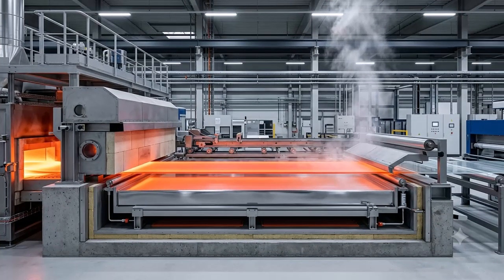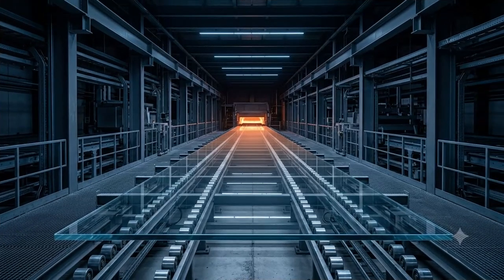How do we get glass so perfectly flat? In the 1950s, Sir Alistair Pilkington revolutionized the industry with the float glass process. Molten glass is poured onto a bath of molten tin. Because glass is lighter, it floats on top like oil on water. Since the surface of liquid tin is perfectly level, the glass becomes perfectly flat on both sides, requiring no expensive polishing.